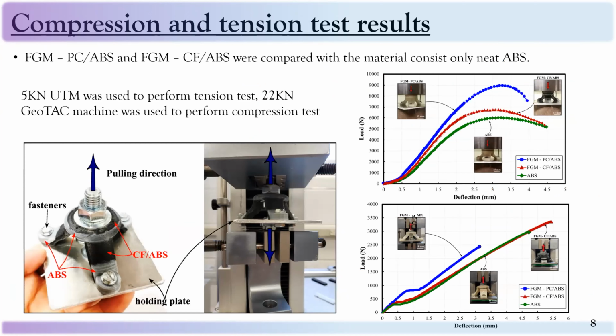And this is the test setup for the mounting bracket sample part, which undergoes tension and compression loads. Over here, you see FGM polycarbonate ABS and FGM carbon fiber ABS were compared with a material consisting of neat ABS. The polycarbonate ABS pair was used for comparison purposes because it consists of dissimilar material interfaces. The first graph shows the compression test results, and it can be seen that one part has various compression responses under the same loading conditions, which helps us design functional composite parts with tailored mechanical properties. The FGM polycarbonate ABS part also showed 50% more load-bearing performance than neat ABS under compression load cases.